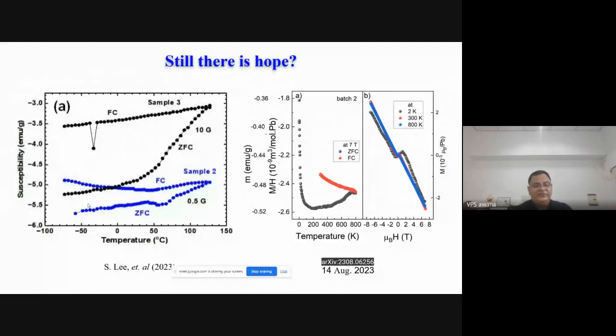This is interesting, in fact. If we see the ZFC and FC of S. Lee et al., dated 14th August 2023, their sample shows there is a good hysteresis in FC and ZFC at 10 Gauss, even 0.5 Gauss also.